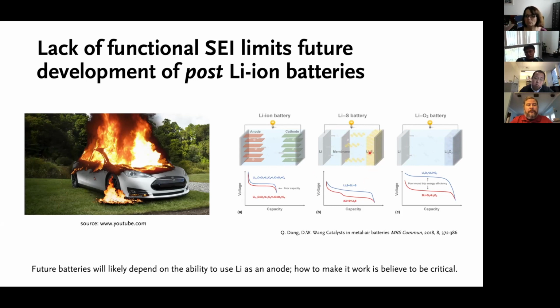We need to switch to, for instance, two ideas that have been floated around and further developed: lithium sulfur battery and lithium oxygen battery. What's very important is that for this new concept, that's why I have this post-lithium ion battery in my title here, for this new concept to work, we really need to replace the anode. Using graphite will not make the cut. And the only metal that's going to work to break the barrier will be lithium. For instance, the Department of Energy has a very large project called Battery 500. It's called 500 because their goal is to reach 500 watt hour per kilogram. It's a convenient number to remember.